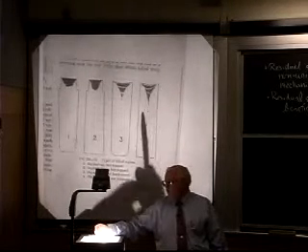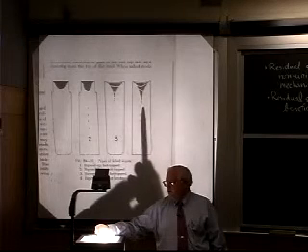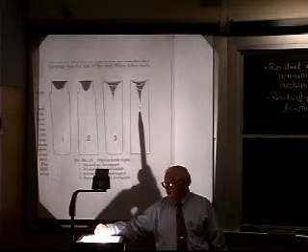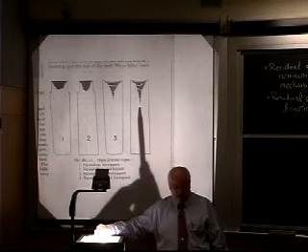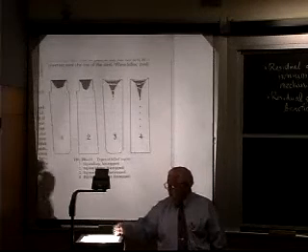I'm not going to go through it, but in prior years, I spent about half a class going through the failure of a tail shaft in a liquid natural gas tanker, and it was because of this type of solidification defect that occurred before they forged the shaft for the propeller of the ship. So that's just very simply ingot casting.